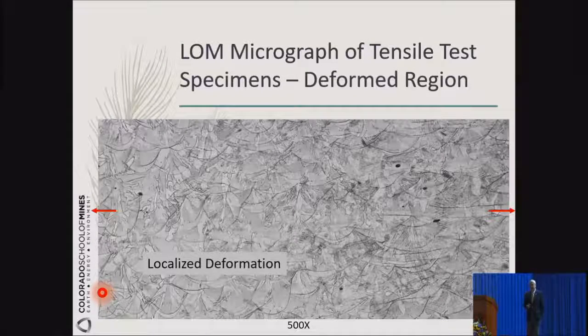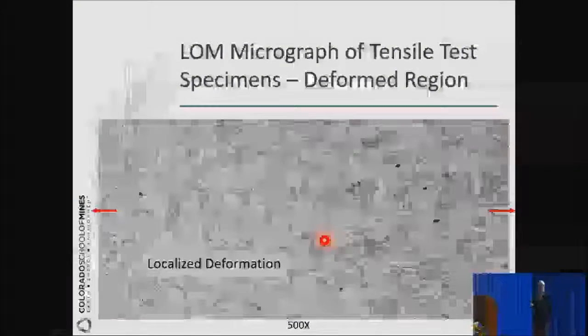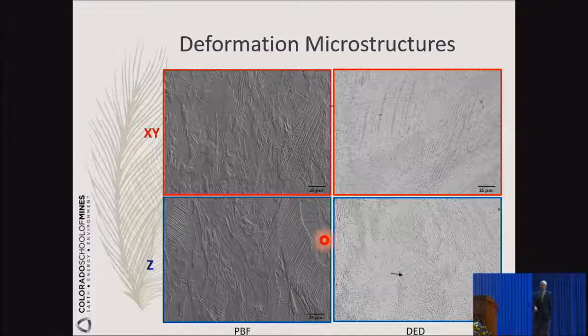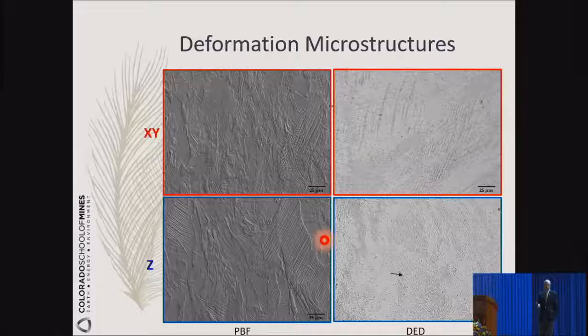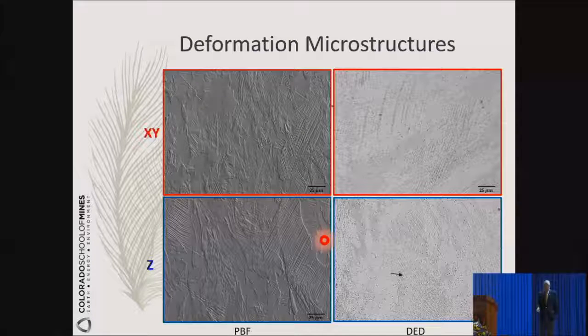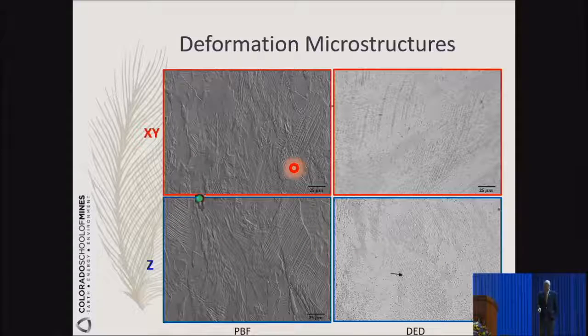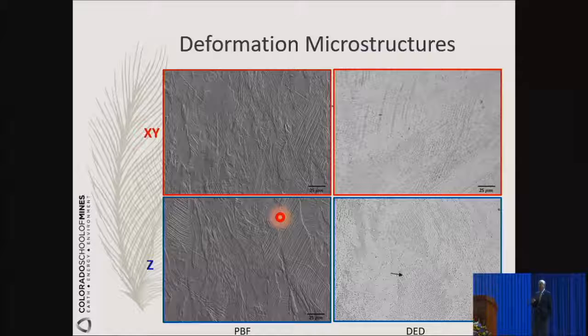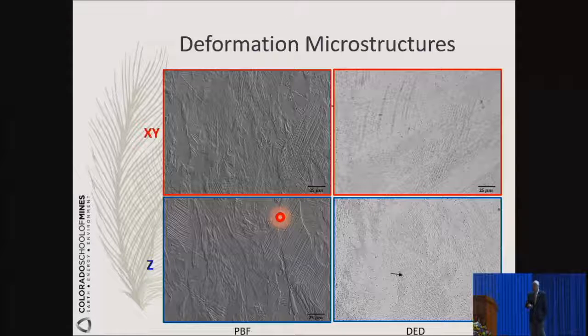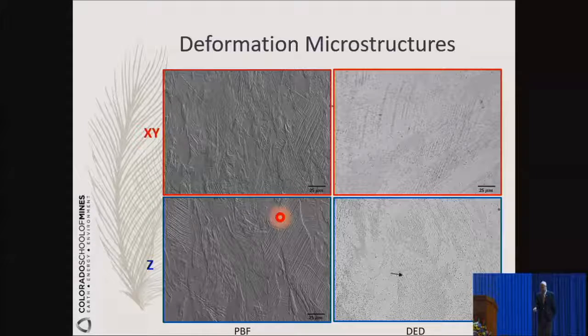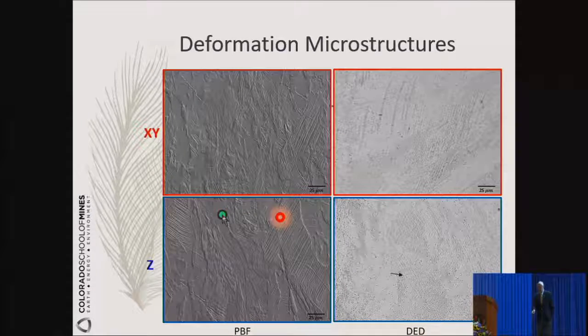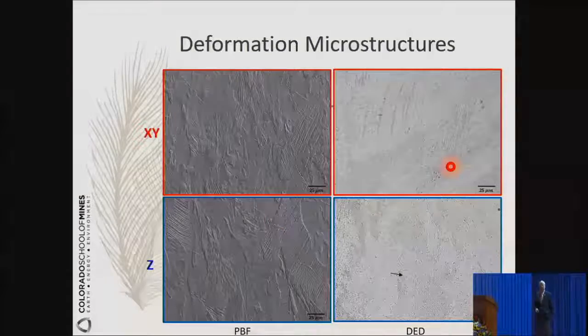And then we notice that there is some localized, preferred deformation. Is it related to the different microstructures? In this case, this is the tensile direction. And you notice that going across the sample, there are regions that have localized deformation. Taking a look at the light micrographs, the Z and XY represent different views of the materials. You see some features that could be identified as maybe twinning products, which is not as visible in the DED. On the left-hand side is powder bed fusion, on the right-hand side is direct energy deposition.